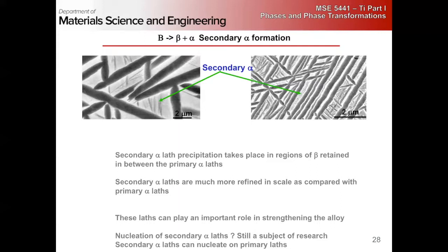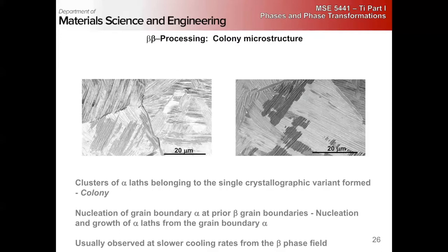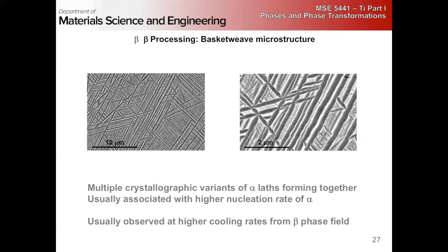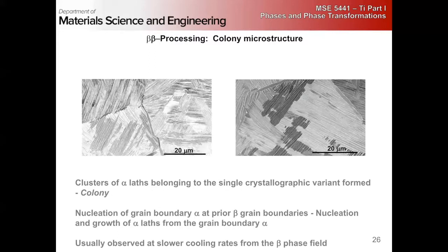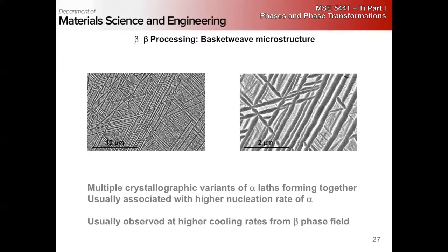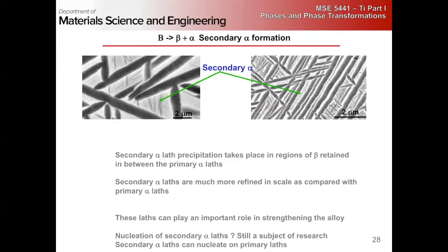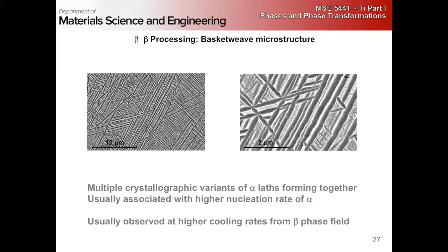So, will it come from the solutionizing temperature or alpha plus beta? The alpha plus beta. Secondary alpha. Right. So this is going to be cooling from the pure beta phase field, from the solutionizing field, because you're going to grow your Widmanstätten laths on cooling. So I would say the skeleton of your structure is formed there.